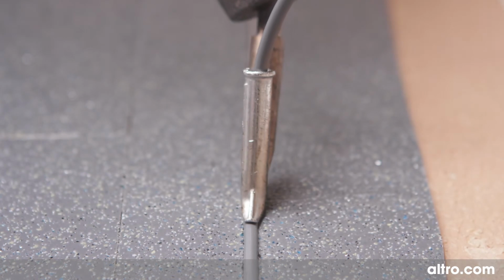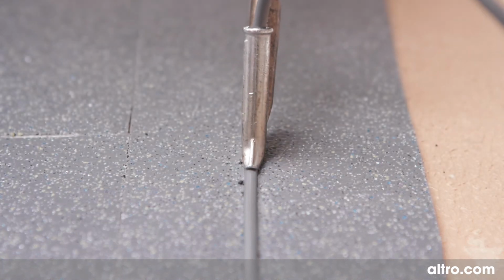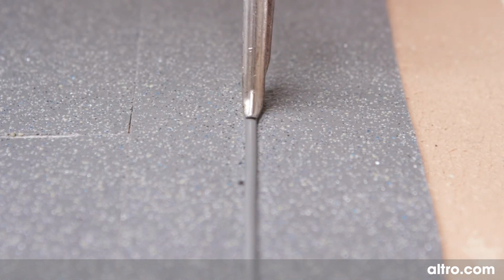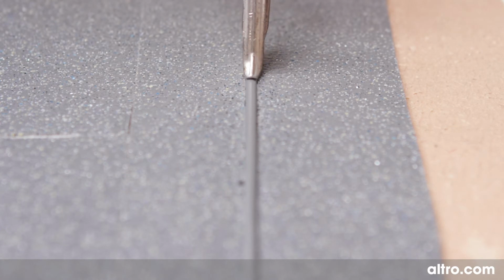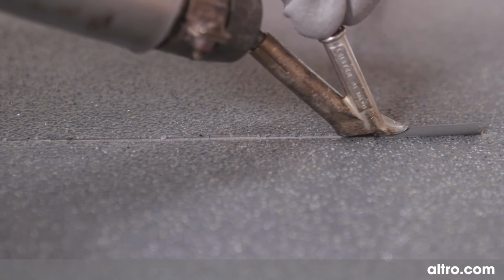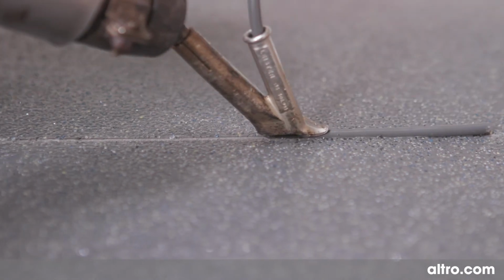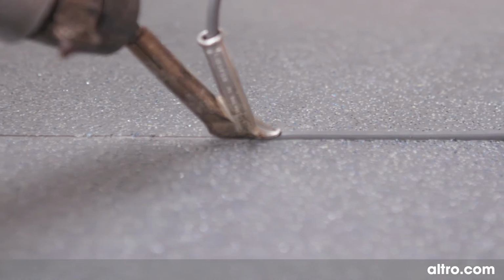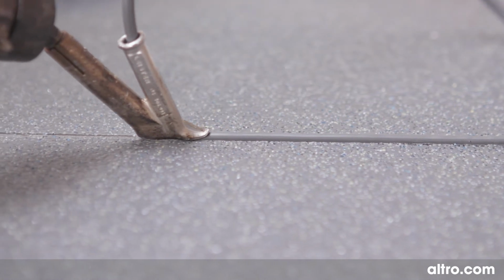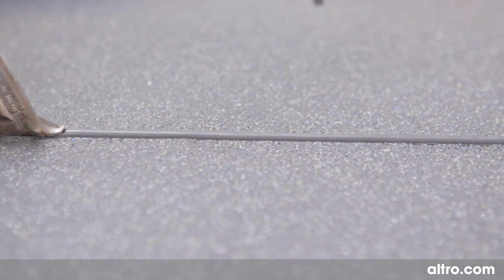A round profile welding rod is for welding flat seams. If you're scorching the floor, move slightly faster or turn down the heat. The rate of speed should be about 3 linear feet per minute. Watch for the wash forming on both sides of the weld rod. A wash is where a small amount of flooring material comes up either side of the weld rod during welding. If you don't see a wash, slow down and/or turn up the heat.